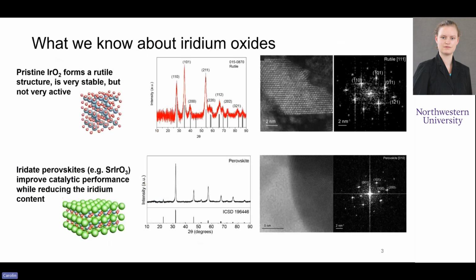So what we know about iridium oxides. The base iridium oxide forms a rutile structure, just like titanium oxide does. It is quite stable to the extreme oxidative environments in a water electrolyzer. It's not all that active. And so over time, there have been many variants of iridium oxides developed to increase activity and durability.